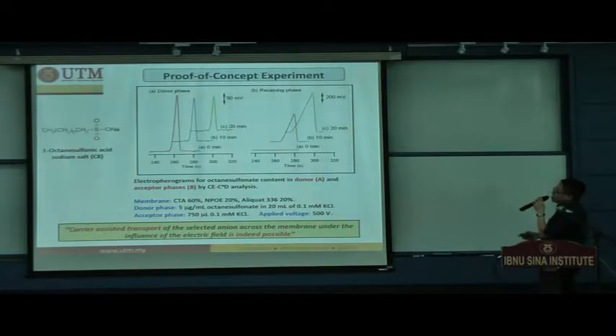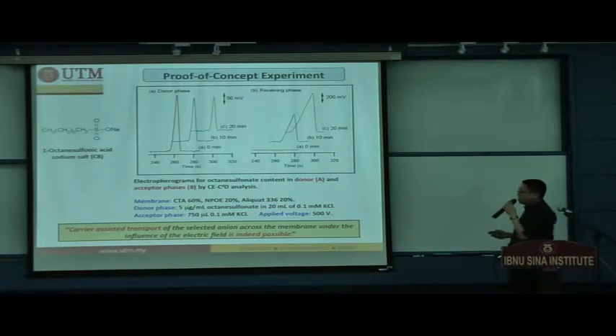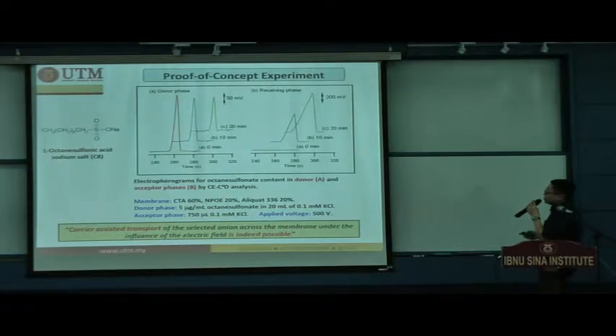You can see that the amount of octane sulfonic acid in the sample phase reduced tremendously along the extraction time. And from the beginning of nothing present in the acceptor phase, the amount of octane sulfonate increased tremendously. The different scale for the signals represents that there is up-concentration of the octane sulfonic acid from the sample to the acceptor phase. From these observations, we were able to prove that carrier-assisted transport of the selected anion across the membrane under the influence of the electric field is indeed possible.